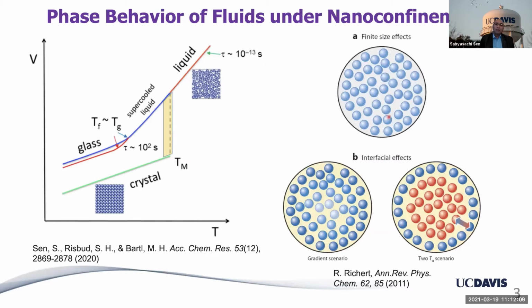So the point is, what could be happening in terms of the structure of the liquid, right? Because that will be controlling whether it will be going into a crystalline state or a glassy state, how the melting point will change or Tg will change, etc. And there one needs to consider two effects. One is just the size effect, which is also the so-called Gibbs-Thomson type effect, where we know that, for example, for first order transitions, we need to worry about change of vapor pressure with curvature, and the tighter the space, the higher the curvature, and therefore, the lower could be the melting point. That's why nanoparticles melt at a lower temperature than their bulk counterparts. So that's a size effect, but the structure is fairly homogeneous throughout the confined space.